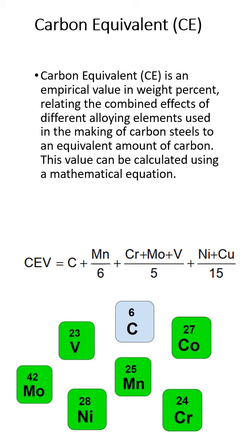Okay, this tells me, do I have to preheat this stuff or don't I? It tells you, okay, this stuff's got a carbon equivalent of about 0.65. Well, I should probably throw some preheat on it before I attempt to weld it. Or the carbon equivalent comes back and it's low enough that you can make a weld without any significant amounts of preheat or post-weld heat treat. So that's what a carbon equivalent tells you. It gets you in the ball game.